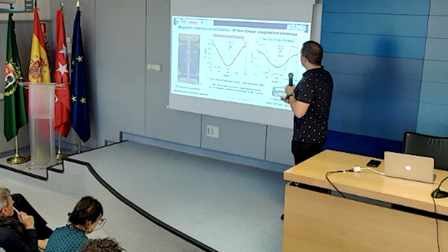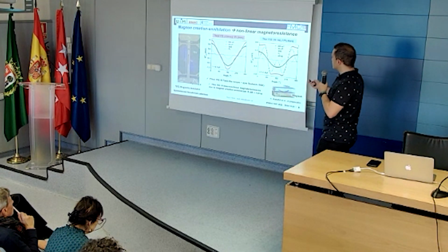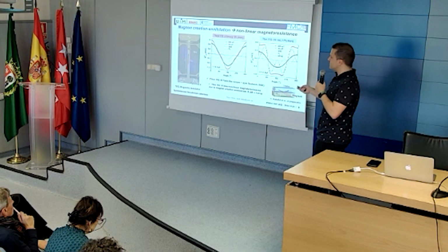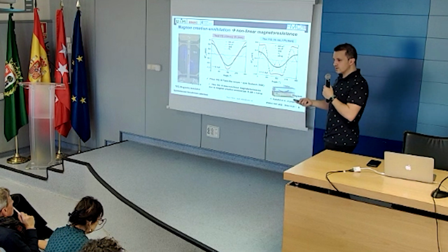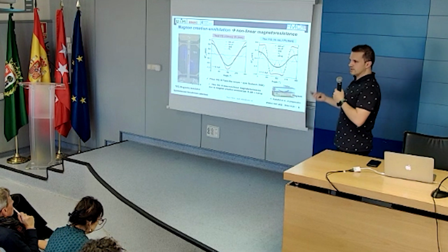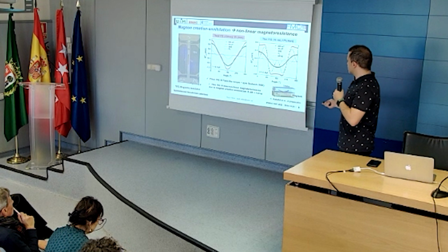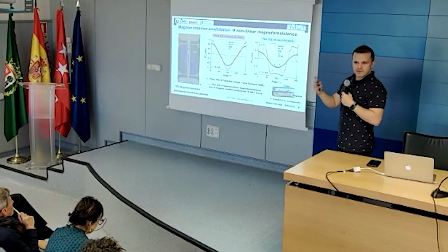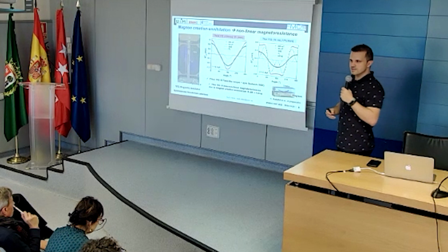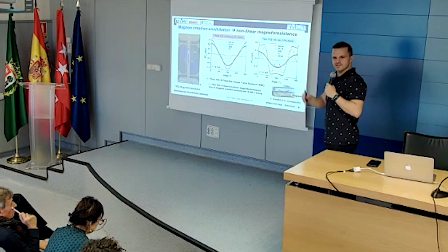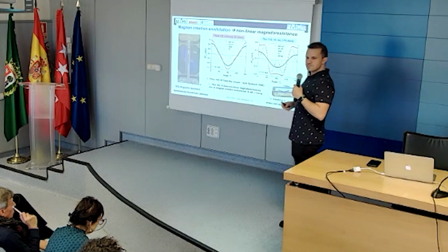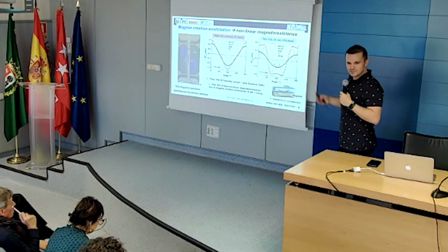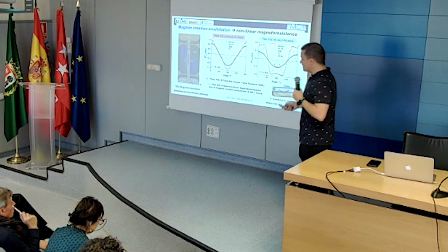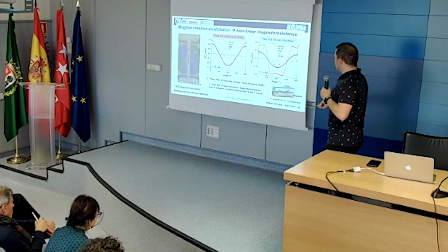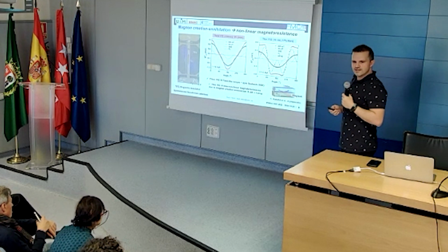Okay. And now, if you take this yttrium iron garnet, instead of a thick one, you take a very small one. We see the effects that we saw for the thin one and for the thick one, but we see additional magnetoresistance effects, and that's something related to magnon creation and annihilation effects. So maybe Akash can help us a little bit with understanding this and the thickness dependence, because it's not just 1/thickness, so not just magnetic volume, it's a little bit more than that. We are still preparing and trying to make fits.